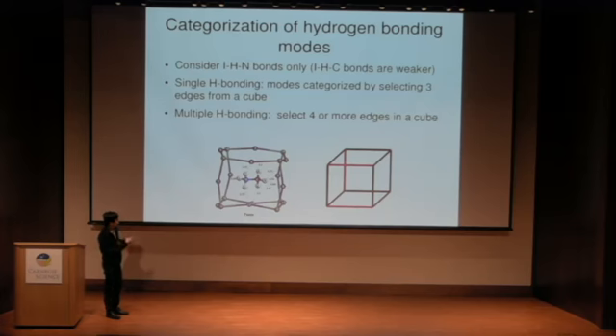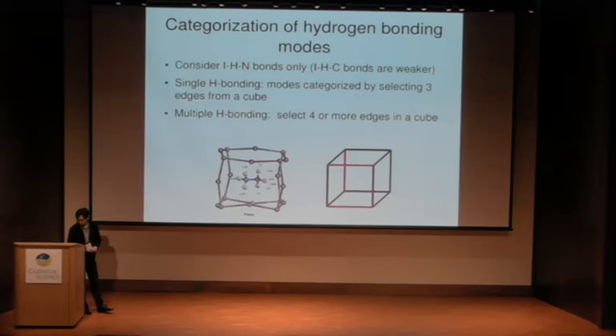Basically, I abstract these bonds out to a problem of choosing edges on a cube. So if there are 3 hydrogen bonds, meaning that all 3 are singly bonded, I'm basically choosing 3 edges on a cube. And if there are more, I can choose 4. Very rarely there is 5. Most of the time it's 3 or 4 for the structures in my database. I'm explaining this notation because this will be the degrees of freedom in my effective model, which I'll explain later on.